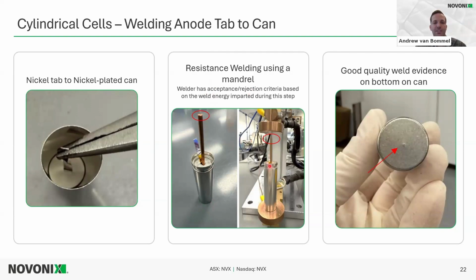This welder has acceptance and rejection criteria based upon the weld energy imparted to that weld. So this will let the operator know if it was a good weld or not. They can also look at the bottom of the can, and seeing that dimple is more evidence that there's a good weld on that anode.